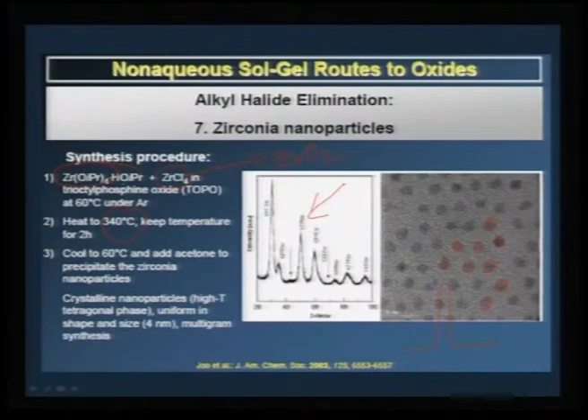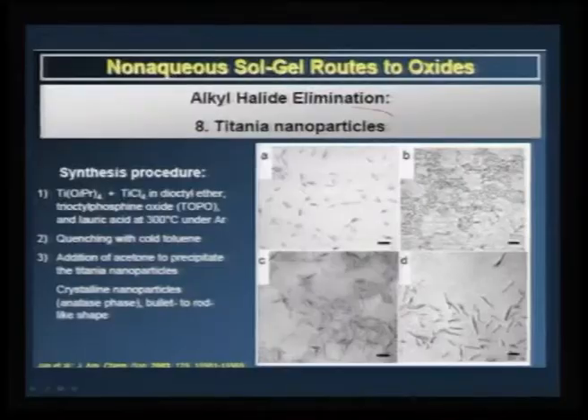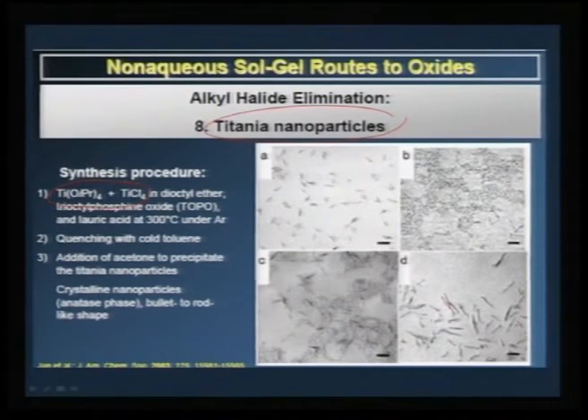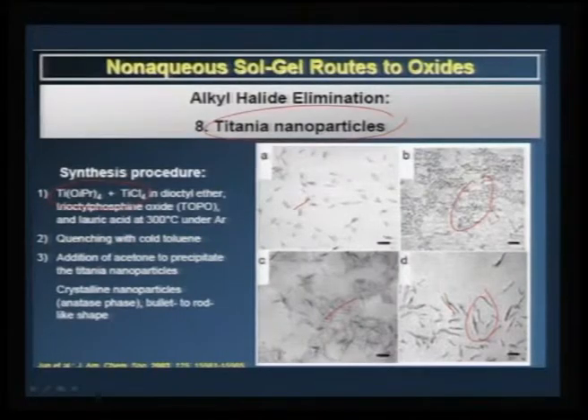Again for titanium nanoparticles, use titanium chloride and titanium isopropoxide — you can see rod-shaped nanoparticles formed with different temperatures and gelation times. The gelling time is a kinetic growth approach; you can restrict the gel formation over a period of time, and depending on the gel formation you can determine the length and breadth of your nanorods. Therefore, gel aging is very important while you transform it into an oxide.